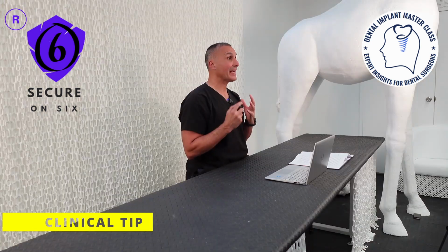However, 29.5% happened within the first 2 seconds and 40.2% within the first 10 seconds. In a clinical setting, it is advisable to take this data and to retighten freshly placed abutment screws either within a few seconds or a few minutes after post-fitting, or alternatively the following day, whichever is practicable.